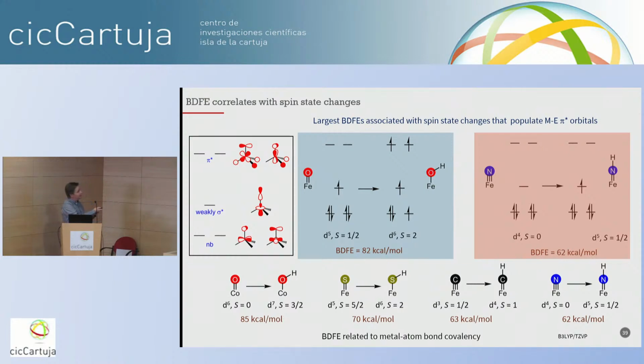And so one reaction, of course, is hydrogen atom transfer. And I showed earlier that for iron oxo, we can pull off a hydrogen atom. We go from low spin iron 3 to high spin iron 2. And then for the nitrides we looked at a long time ago, the computed first structure is actually low spin. And so what we find is actually the bond energy here for the OH bond is much stronger than this bond energy here. So we'll try to figure out what's behind these differences.